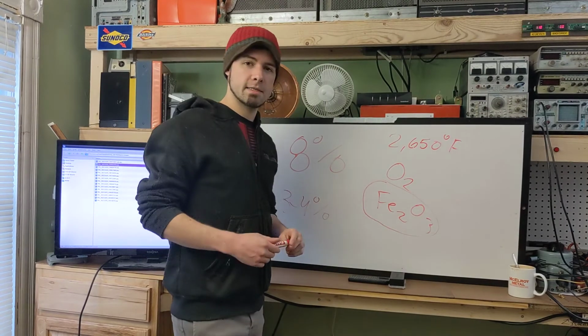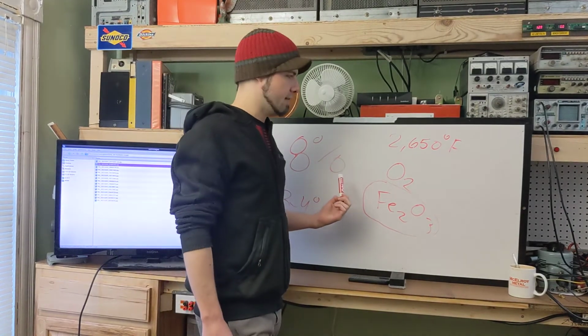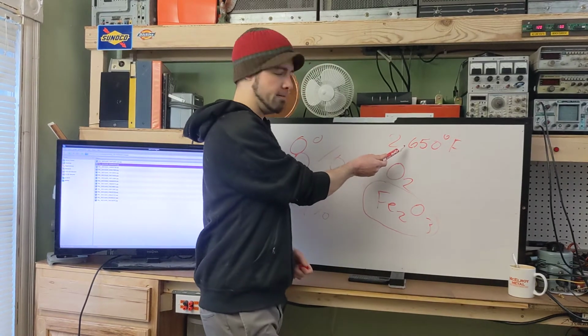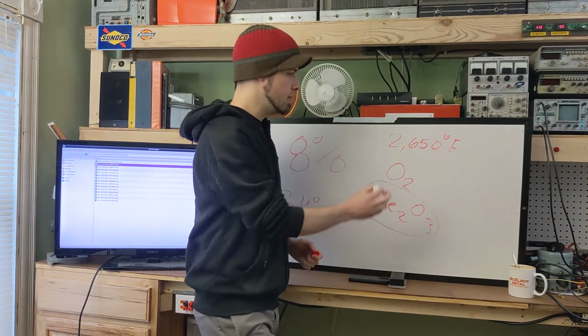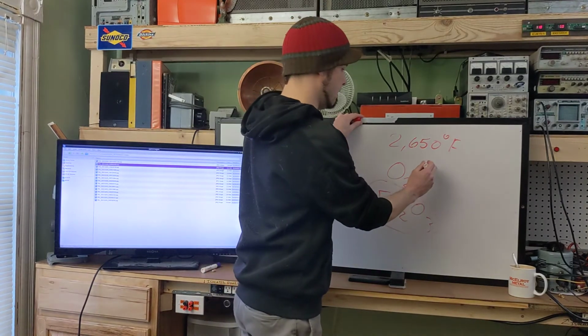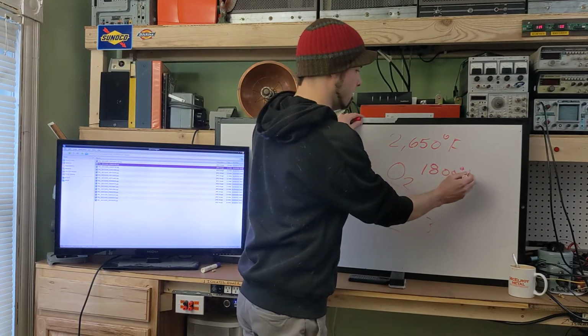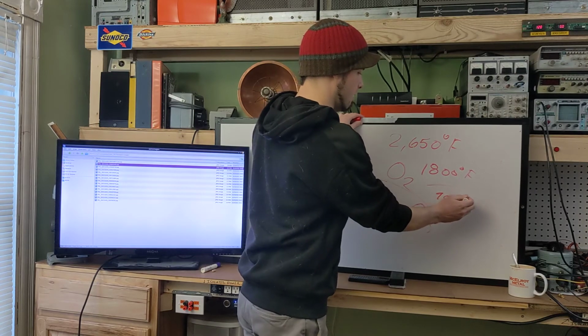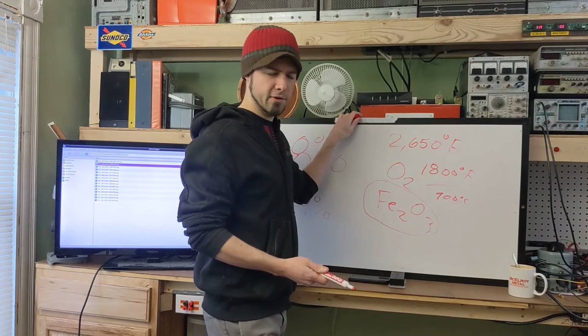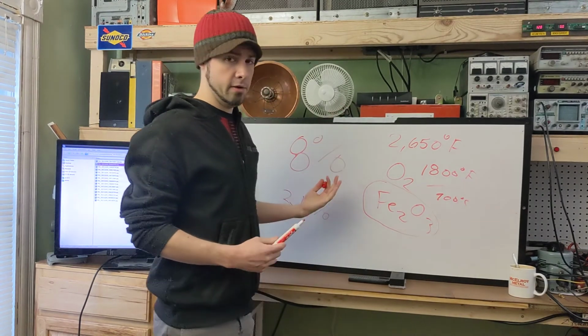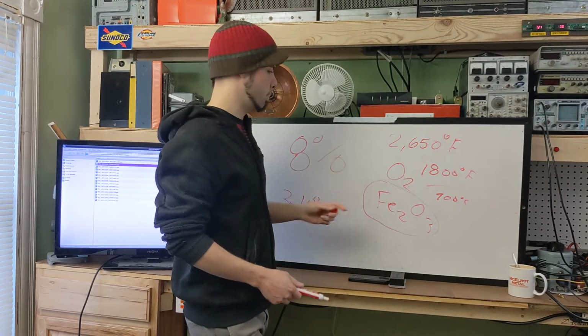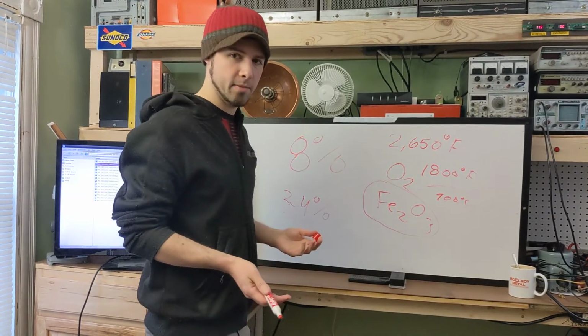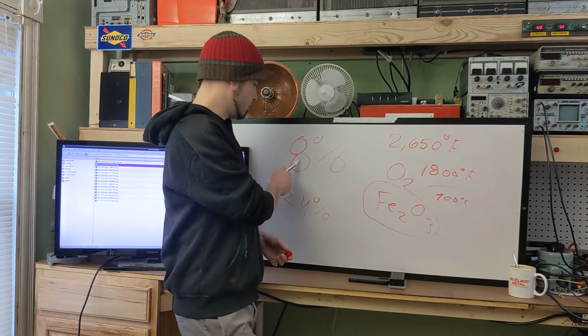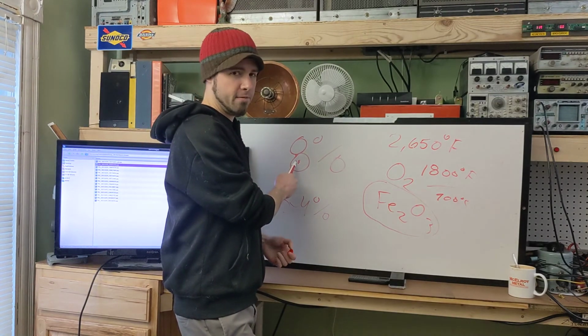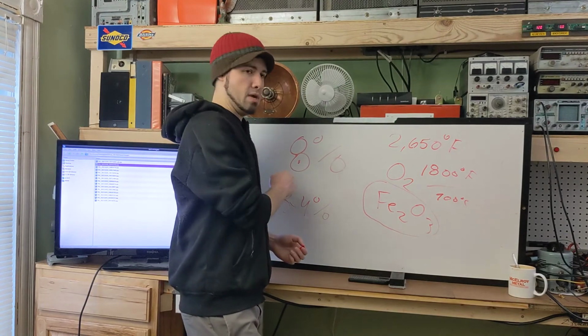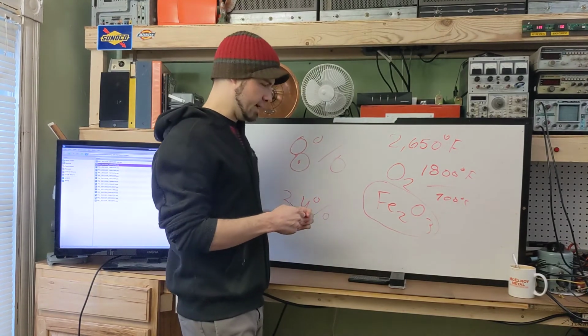The other idea is to go back to cements that aren't as energy intensive. Instead of using Portland cement that has to be fired at 2,650 degrees, you could use lime. Lime only needs to be fired at, say, 1,800 Fahrenheit or 900 Celsius. And the lower temperature results in less energy usage. So you could cut your emissions from the fuel side of things by using a lime-based cement for various applications. So you go from, instead of 45% coming from the fuel, maybe only 25% would come from the fuel or something like that.